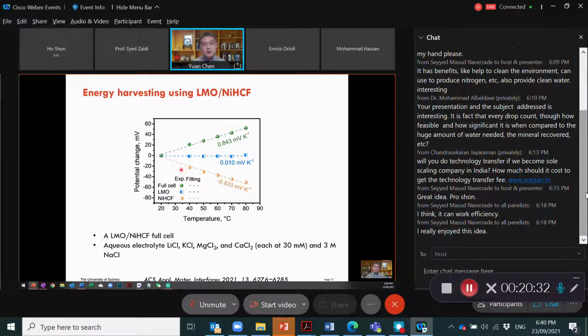For the nickel HCF, you actually get a negative temperature coefficient. And for the LMO, it's actually roughly positive, but quite close to zero. But the good thing is when you pair them together, they get a very positive temperature coefficient, which means we can use this pair of electrodes in an electrolyte similar to the source solution people are using to extract lithium, to harvest energy. So that's step one.